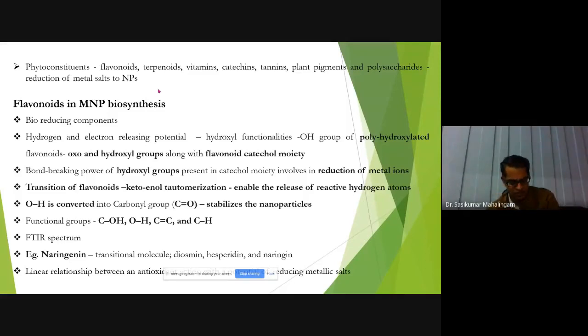If you see the flavonoid biosynthetic pathway, that is the shikimic acid pathway, these flavonoids have come across several chains, several networks in which these flavonoids have been polyhydroxylated. All flavonoids have been polyhydroxylated with one or two hydroxyl groups along with the flavonoid catechol moiety. And this hydroxyl group has the power of bond breaking that is found in the catechol moiety, which will reduce the metal ions. So during this reduction of metal ions by hydroxyl groups, there will be a transition of flavonoids, that is keto-enol tautomerization, keto to enol, enol to keto. During this transition, there will be release of reactive hydrogen atoms.